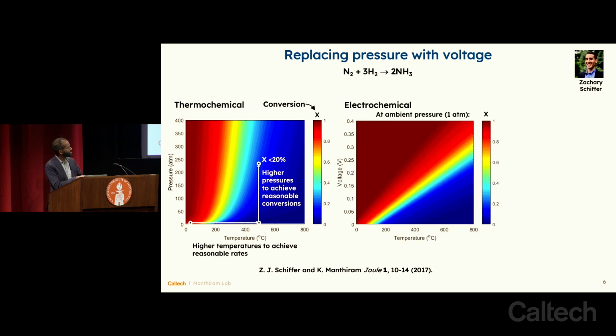And so we can consider instead to use voltage to recover conversion in the place of pressure. This plot has the exact same x-axis. We still have temperature, but we've now placed voltage on the y-axis. And you'll see a plot that looks really different. We could start, for instance, at 500 degrees centigrade. We could now apply a third of a volt going up, and we would reach a region which is deep red in color, near unit conversion, greater than 99% conversion of nitrogen and hydrogen to ammonia, with just a third